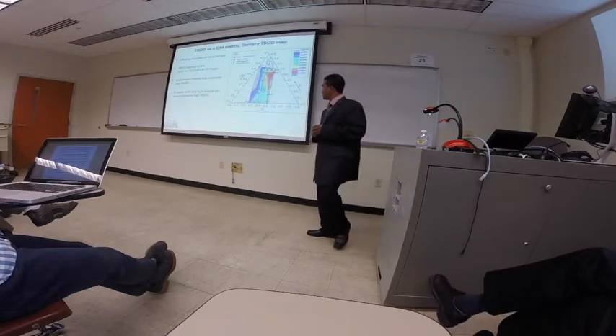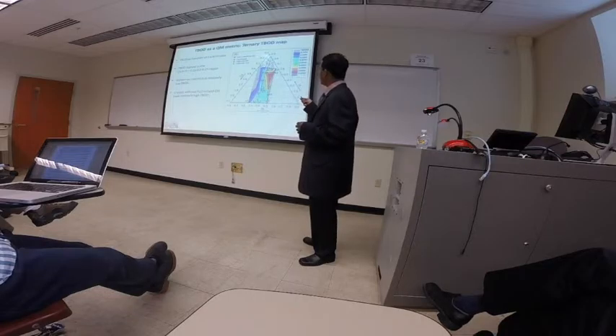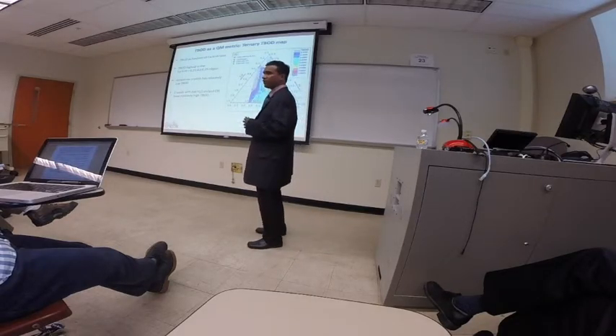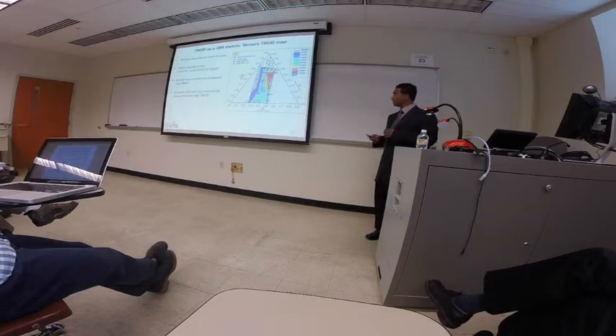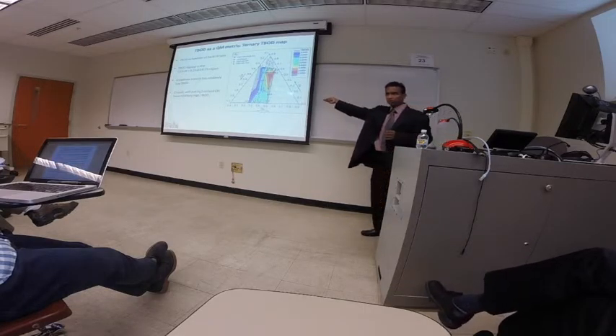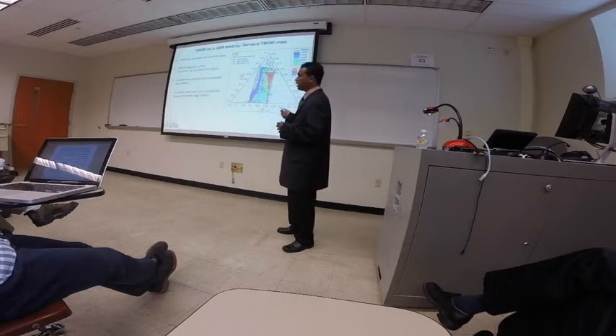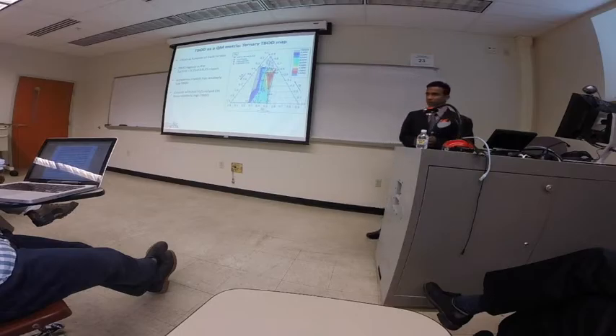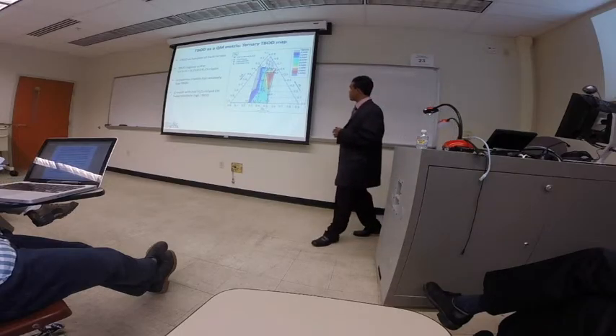So to understand this further, we made this ternary plot for the composition of calcium, silicon, and hydrogen to identify if there's any preferred TBOD regions, because any cement you find has to fall within this triangle. So we wanted to find out, is there any preferred total bond order density regions that we can somehow engineer the chemistry, the composition to obtain.